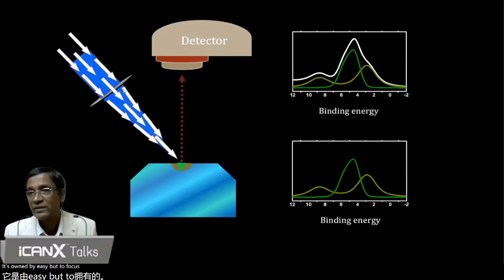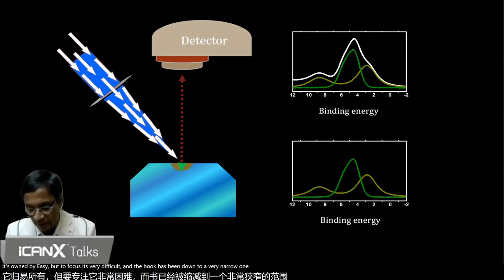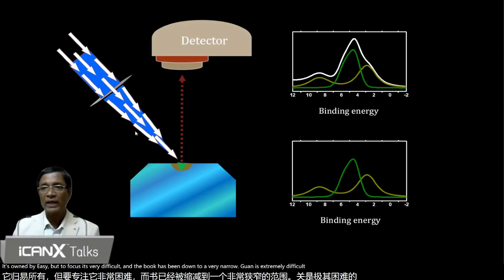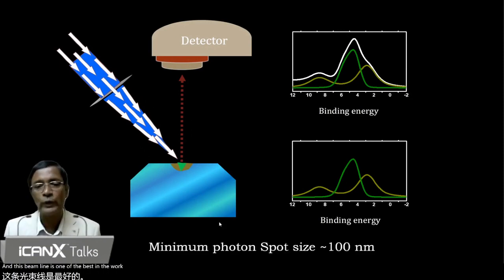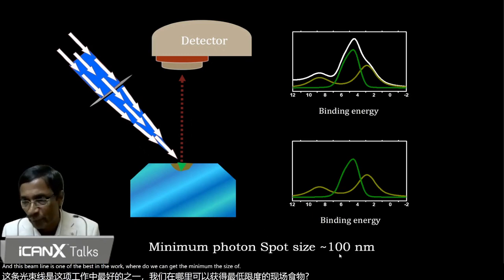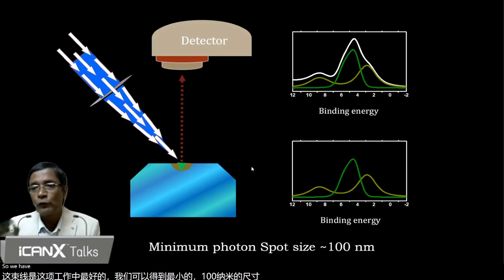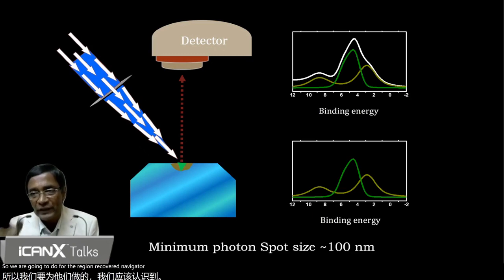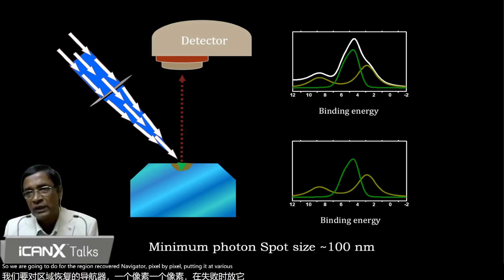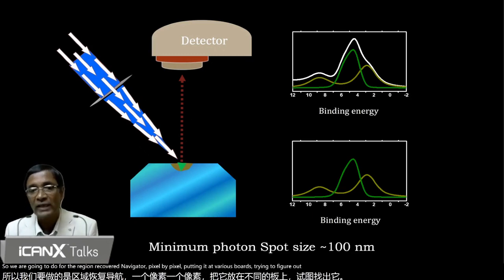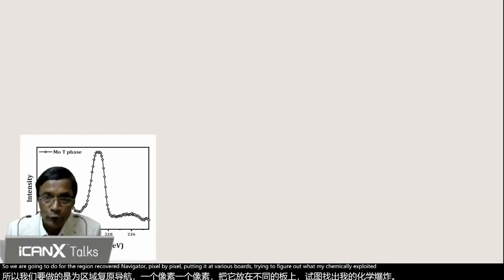It sounds very easy, but to focus X-rays is very difficult, and to focus them down to a very narrow point is extremely difficult. This beamline is one of the best in the world, where we can get a minimum photon size of 100 nanometers. So we are going to do photoemission with 100 nanometers, pixel by pixel, putting it at various points, trying to figure out what my chemically exfoliated sample looks like.